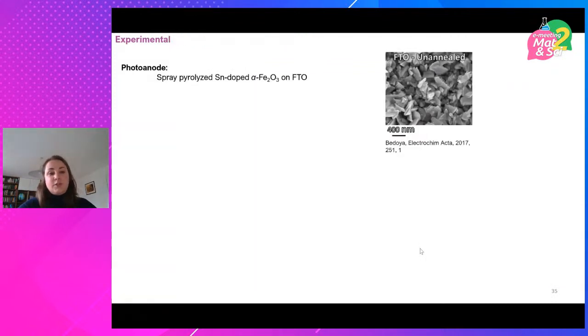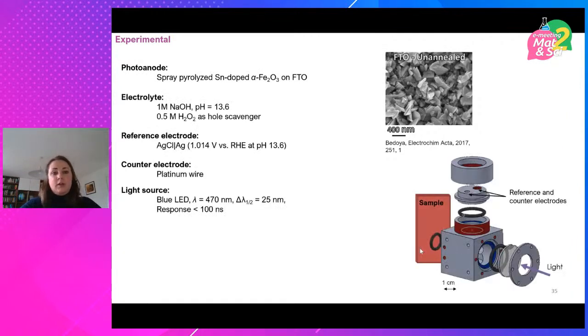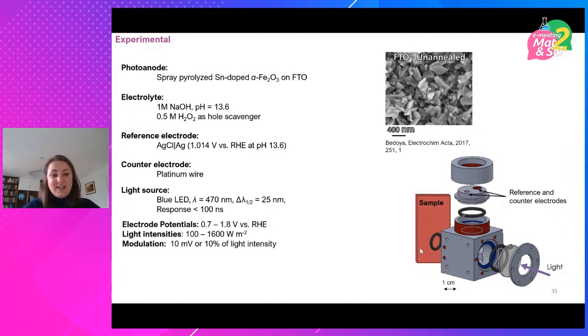And he was able to do this really systematic study using spray pyrolyzed tin-doped hematite on FTO. He used a consistent electrolyte, so either 1 molar hydroxide or 1 molar hydroxide with scavenger. Same reference electrode, which he checked remained stable for all the measurements. Platinum wire counter electrode. And then instead of white light, he used LED, which he concluded actually gave a more stable light source. He determined that even use of mechanical shutters, for example, for chopped measurements, was too slow, and so introduced enough error that affected the efficiencies that he actually calculated in the end.